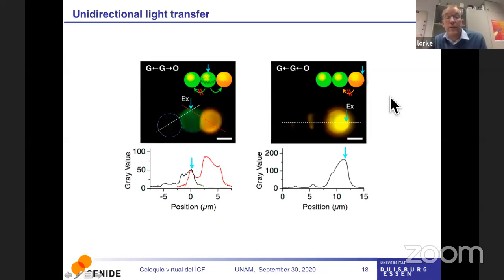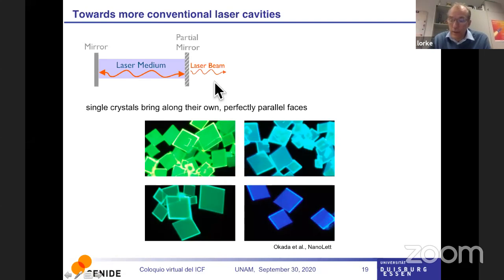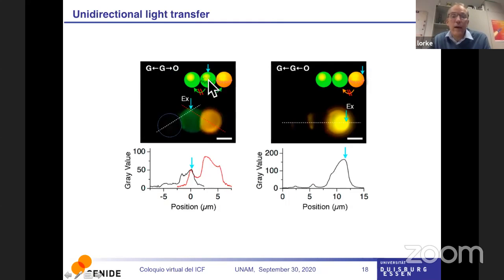They did a lot of experiments. The two PhD students that were working on this, one from Japan and one from Germany, were able to push these spheres around with a tiny little needle too. Here you have 3 of these spheres, and you illuminate the one in the middle, and you see that the light is transferred from the middle to the right one, but not to the left one.